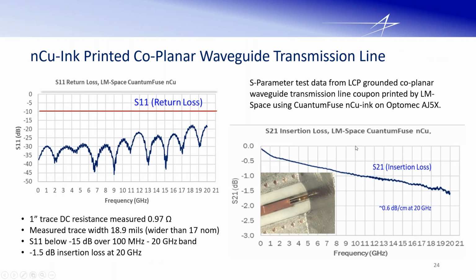All right. So this is an example. Now this happens to be aerosol jet printed nano copper. This happens to be a nano copper called CuantumFuse that Lockheed Martin makes. So there was a lot of interest in that. And this coupon is designed to be tested up to 20 gigahertz. That's what we've been doing initially. We're obviously interested in higher frequencies, but a lot of our millimeter wave type of work is broadband, and it goes from megahertz up to about 20 gigahertz. So that broadband region we're interested in.